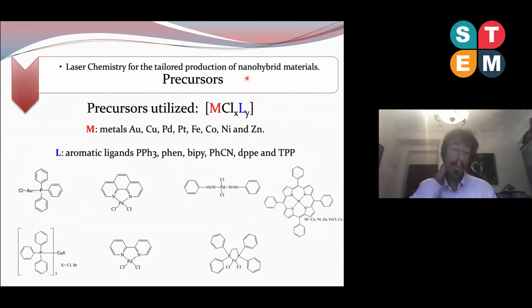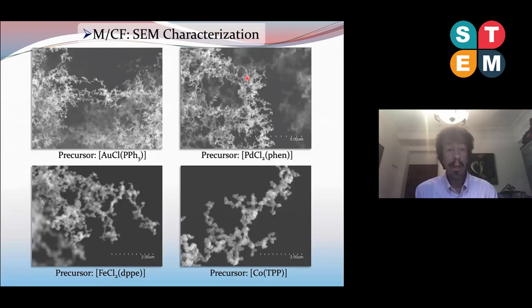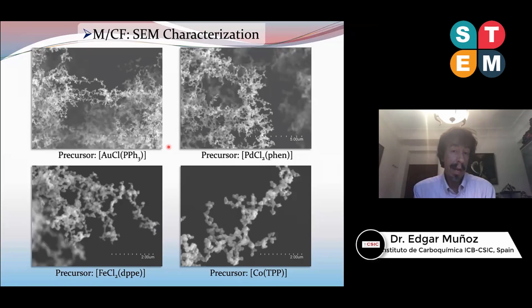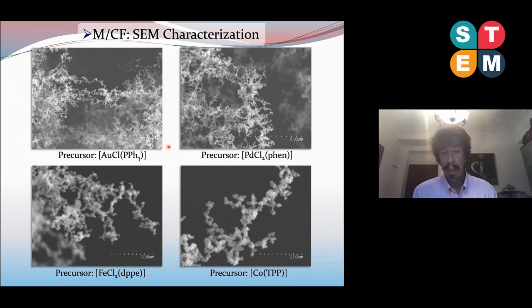So we started working with gold organometallic compounds based on phosphines, but we wanted to extend this work to other kinds of organometallic compounds with other ligands and metals. And we realized that all these materials resulted when doing the laser ablation of these organometallic complexes. In all cases, we obtained different kinds of metal carbon foams, so we can change the metal composition by changing the metal of the organometallic complex that was irradiated by laser. And then we could use the organic ligands as carbon feedstock for the production of these carbon foams.